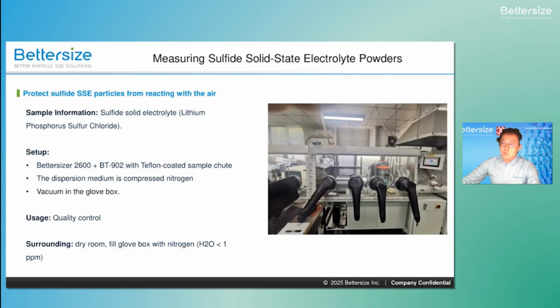Let's look at a real-world setup for quality control of sulfide powders. Here, the dry dispersion module is installed inside a nitrogen-filled glove box with a Teflon-coated chute to ensure sticky powders flow smoothly. You will also notice the vacuum cleaner integrated directly inside the box. This captures the dispersed powder immediately after measurement, allowing for sample recollection and preventing the glove box filters from getting clogged. And during the whole process, no powder was exposed to any moisture or oxygen.